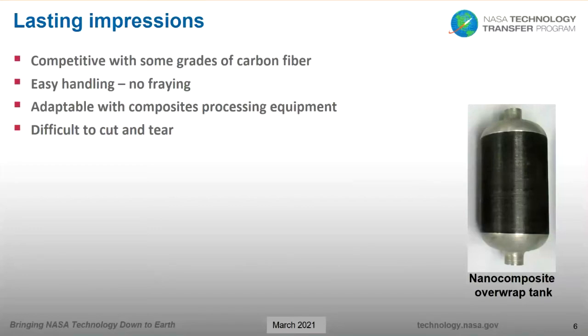And because of its fibrous format, the nanotube yarn was compatible with basic polymer composites processing equipment. The most impressive characteristic of the nanotube that I noticed was how a single yarn filament was extremely difficult to cut and tear. It was almost like fishing line.